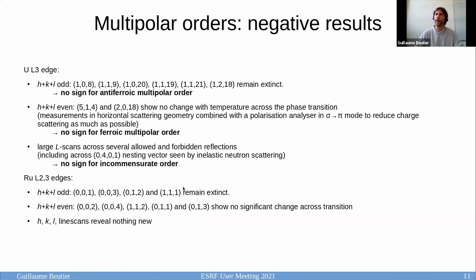So, like everybody else, we had negative results on the multipolar orders. Not really a big surprise, you would say. So we looked at many things. We looked at many forbidden reflections of the HKL type, and there was really nothing over there. We also looked at allowed reflections, in case the signal would be a ferroic order. But to do that, you need to get rid as much as possible of the vastly superior charge scattering. So for that, you would scatter in horizontal geometry and use the polarization analyzer to reject much of it, but we didn't see anything. We did large L scans also to look for other possible propagation vectors, but didn't find anything. We did similar work at the ruthenium L2-3 edge, which has not been done by anybody else, I think, before, just in case there was something to see over there, but we didn't really see anything new.